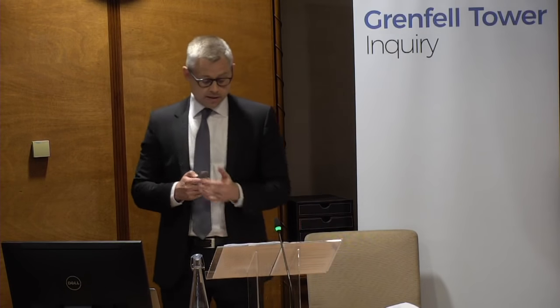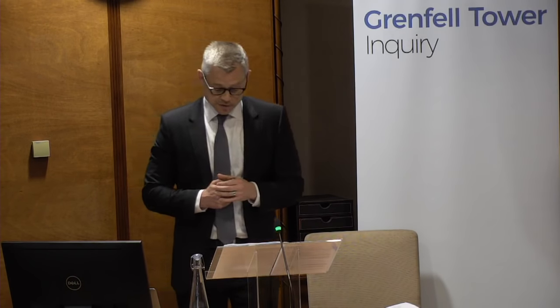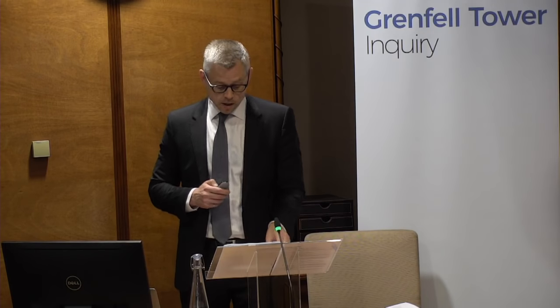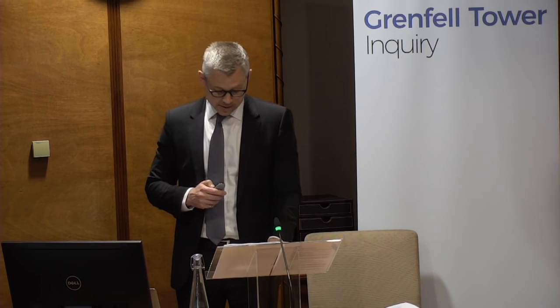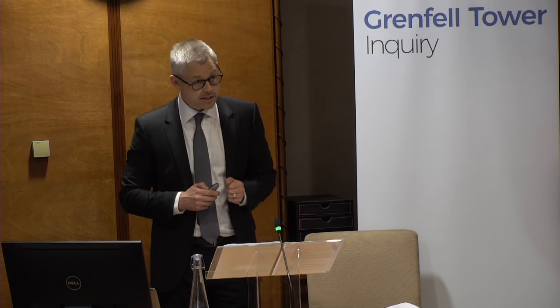You get the point, I hope. For a thermally thick fuel, when exposed to a heat source, the surface temperature of the solid material will begin to increase. The rate of increase is determined in part by the physical properties of the material. The key parameters in this situation are, first, the thermal conductivity of the material. This is a measure of the ability of the material to transfer thermal energy internally by conduction.